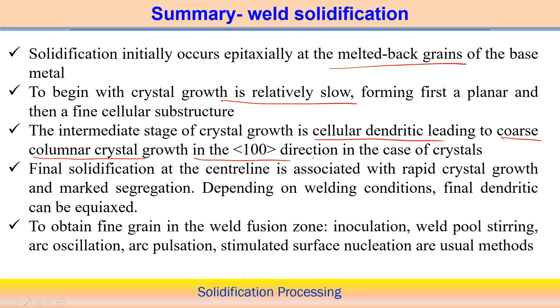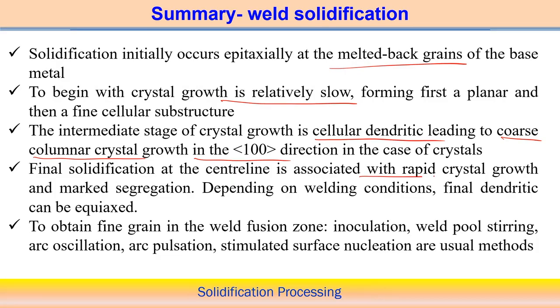And that is usually in the 100 direction in the case of the crystal. So the structure growth starts like that: initially planar growth, then cellular substructure, and then columnar crystals usually grow in metallic materials during the solidification of the welding process. But the final stage of solidification usually occurs at the center line. It is associated with rapid crystal growth, because when reaching the center, the zone is almost at low temperature. So this particular zone is associated with very rapid crystal growth, and therefore there are chances of segregation during the solidification process.